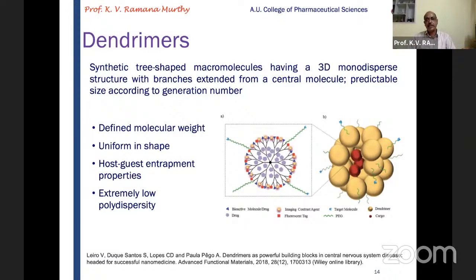The advantage of the dendrimer is they can have different attachments for different branches of this dendrimer, wherein we can have a bioactive molecular drug, or we can have the imaging agent, or some other fluorescent tags, etc. And we can have a defined molecular weight for this dendrimer as per our tailor-made requirements. They are uniform in shape, they have host-guest entrapment properties, and they have very low polydispersity. That means we can obtain a very uniform size.